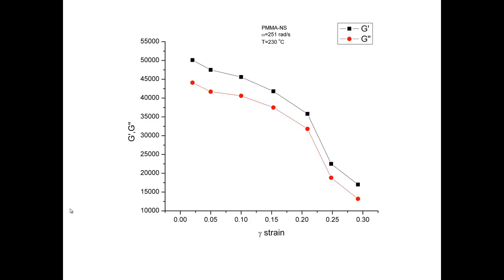Here is a couple of examples of strain softening in a rheometer at constant frequency, so PMMA, and the frequency is 250 radians per second, and the temperature is 230. Recall that Tg is 105 degrees C, so it's far above Tg. And I am plotting G prime and G double prime versus the strain. So I am increasing the strain. The first point that you see on the left are the classical linear viscoelastic range, but as gamma increases, one sees that the G prime and G double prime values decrease, which is